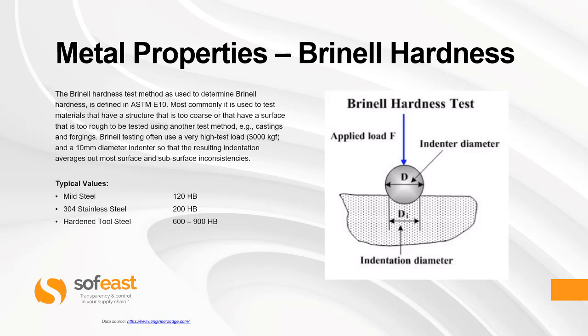Brinell testing often uses a very high test load, 3,000 kilogram force, and a 10mm diameter indenter, so that the resulting indentation averages out most surface and subsurface inconsistencies. Now, typical values for the Brinell hardness: mild steel is around 120, 304 stainless is around 200, and hardened tool steels is between 600 and 900.